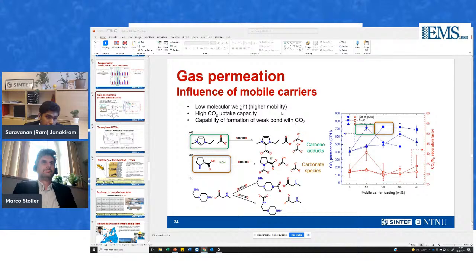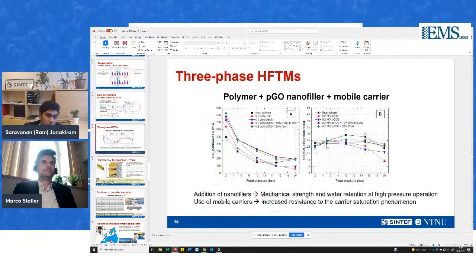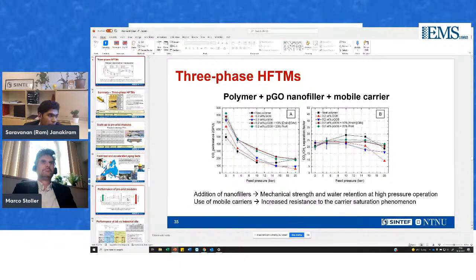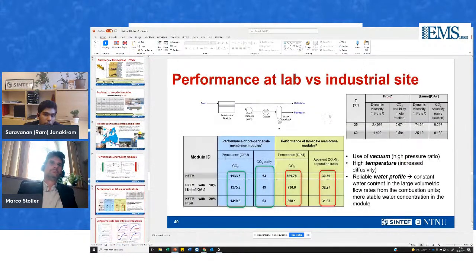So we did use the same 10% concentration with respect to graphene oxide as well, because we know that both of them are hydrophilic, so both of them should be compatible with each other. And it was actually compatible, as you mentioned in your question, that it was a synergistic effect, where we had this porous graphene oxide, which took care of the mechanical properties and also helped with the water uptake, for example, or the polymer chain disruption. And then you have the mobile carrier, which is basically helping you at high temperature for extra permeance.